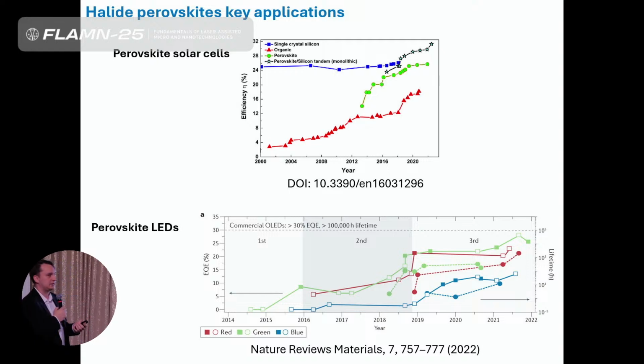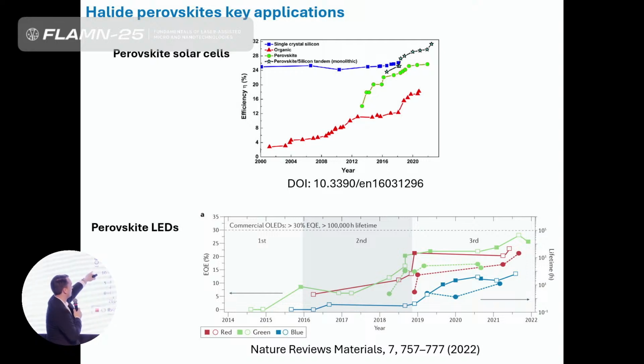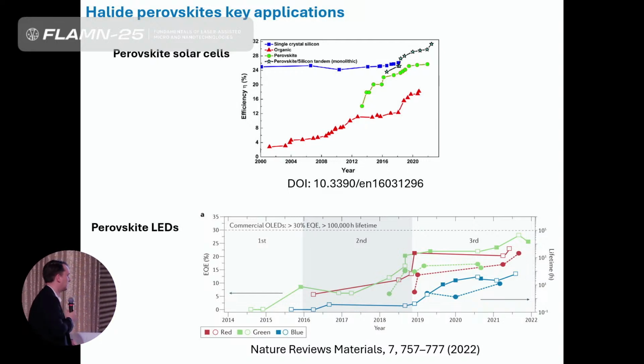And perovskite LEDs started to be developed a bit later. That's why the progress is, despite the very exciting progress in this direction, you also see this dashed line corresponds to the threshold for commercial usage of LEDs, from the point of view of efficiency and lifetime in hours. You see the different colors of perovskite LEDs. They are growing, and green is one of the most stable. They are approaching this threshold, but there is still much work to do to achieve it.